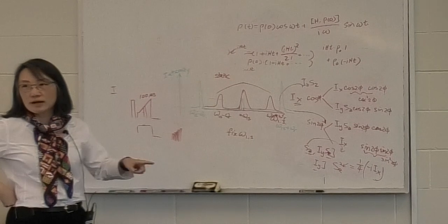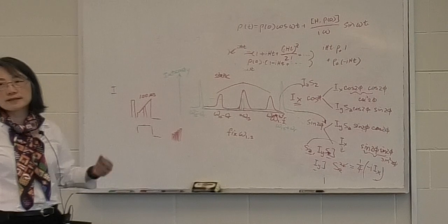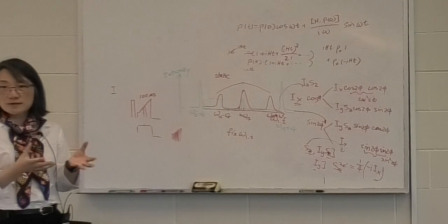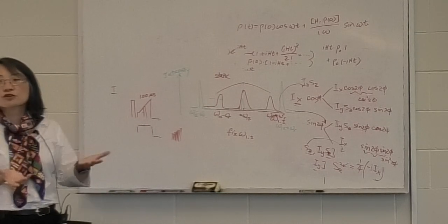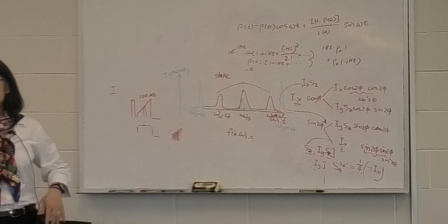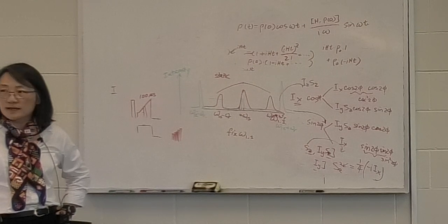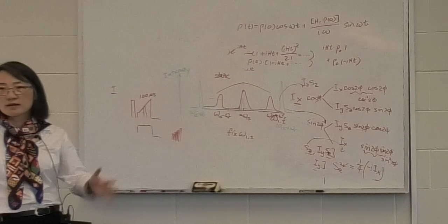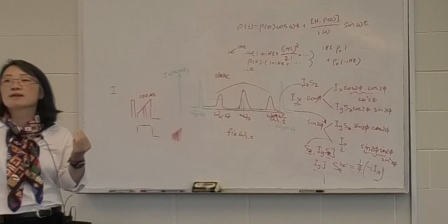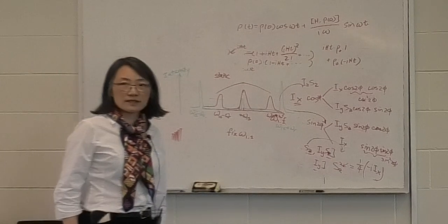In my afternoon's talk about dynamics studies by NMR, you'll see that CP is one of these elements very much used to filter out dynamic things. You see only the rigid species. I mean, CP is not too limiting, too restrictive, but it is helpful. And when we look at heterogeneous biomaterials such as plant cell walls, where you have coexisting highly rigid cellulose and quite dynamic matrix polysaccharide, I want to have everything in my rotor, but I don't want to look at them at the same time, right? So this is a very common element to use to selectively detect stuff.